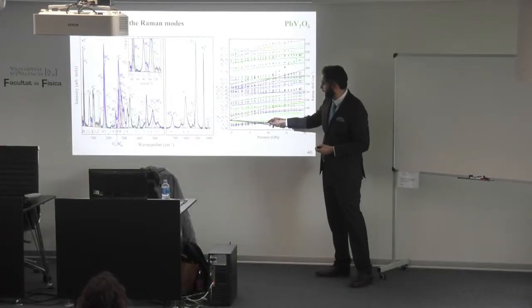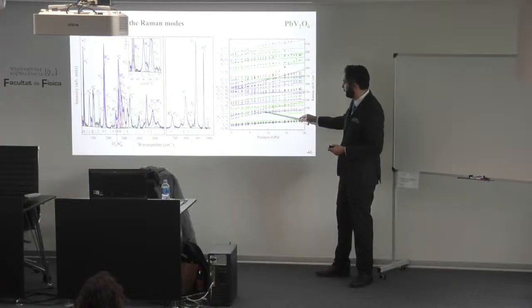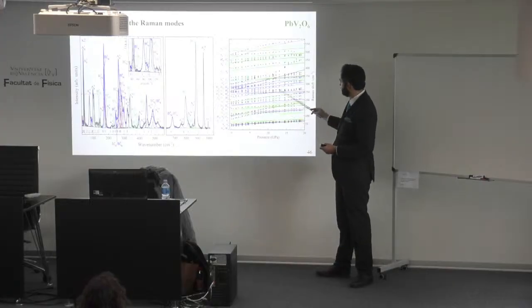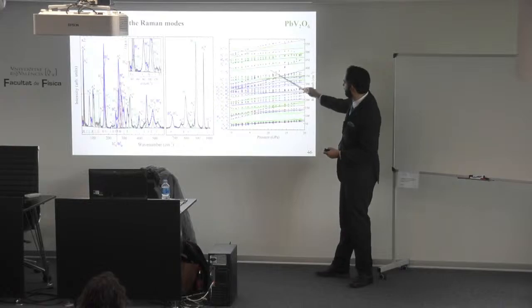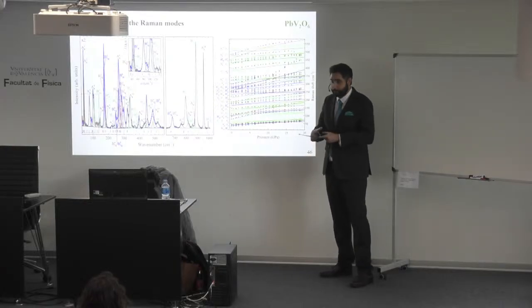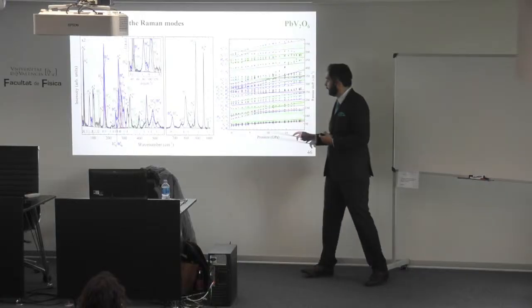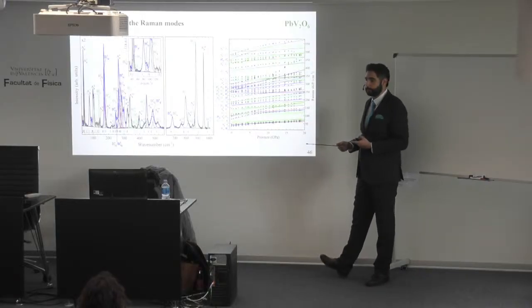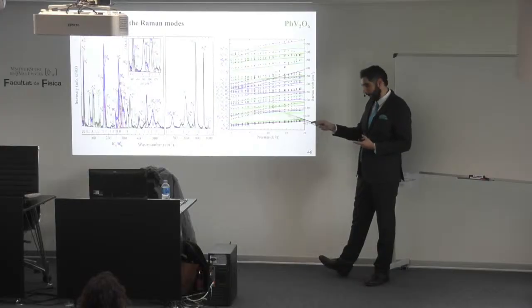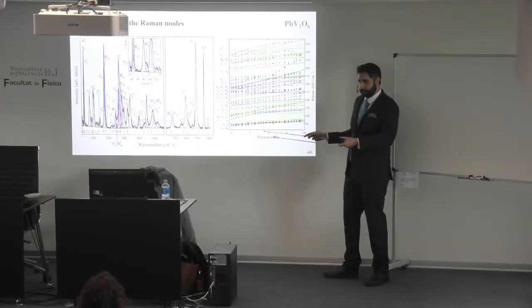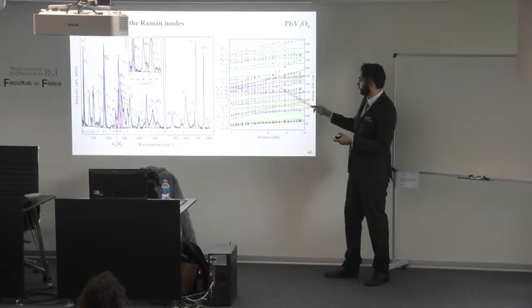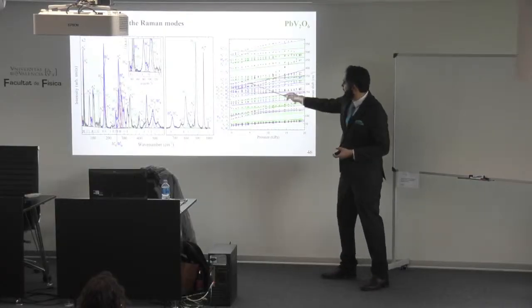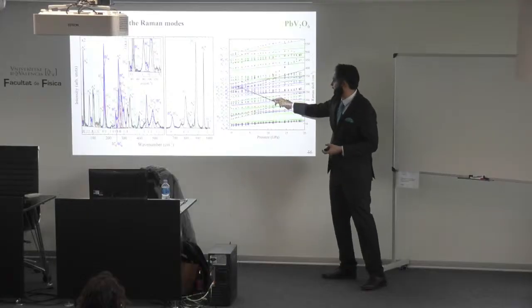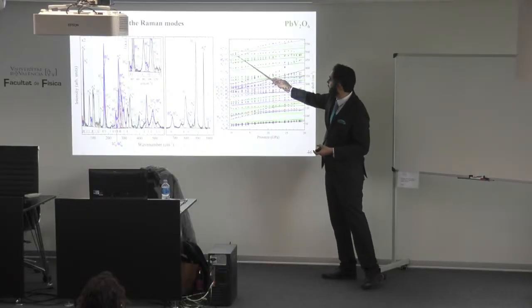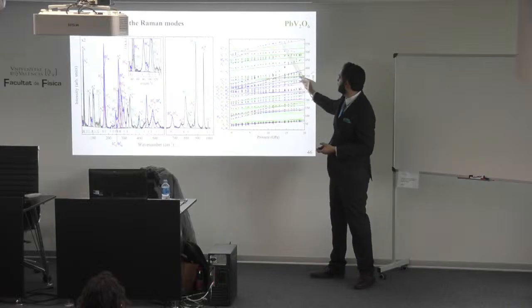As the pressure increases, some of the modes split and merge. If we check here, we have this black one that gets into the other ones. And sometimes you have one that is traveling all along. So the vibrations are affected by the pressure differently. So I can split them. And also, I have the calculations. And calculations also told me how many modes I have there, and also double check me the pressure evolution. This crossing is different. Well, but I expected it. Or this one here also happens.